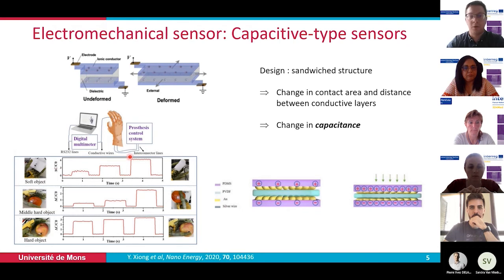First thing to note is that we can distinguish the different softness of the objects, as we have different signals for the different hardness of the object. But we can see that for the soft object, we have quite a lot of noise in the signals, and for the hard object, different pressures lead to, let's say, the same signal, so we cannot distinguish the pressure that is applied on the object when it is too hard. So this is the problem of capacitive type sensors.